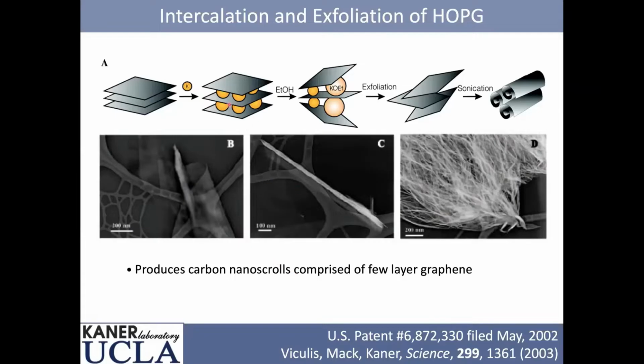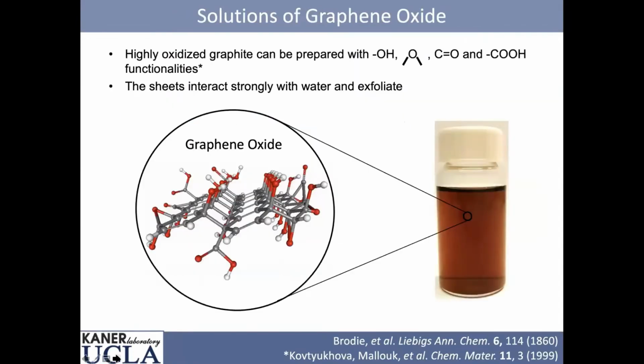However, we realized that this method, although it does make single layer graphene, it also makes 2, 3, 4, 5 layers, all different combinations. And so we realized after Novoselov and Geim did their work that this probably isn't the best way to scale it. But what is a good way to scale it is something called graphene oxide.